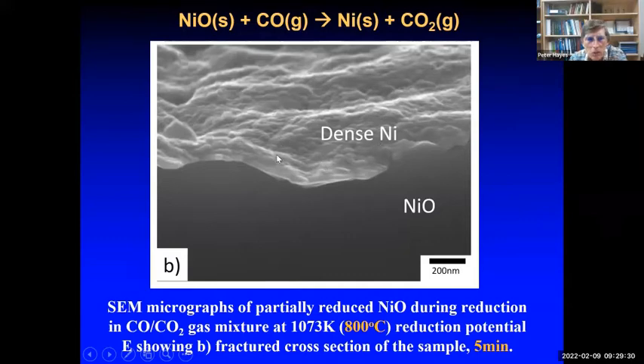So in this case, we actually stop the reaction because the gas can no longer access the nickel oxide underneath. So there's an impervious layer between the gas phase and the dense nickel oxide. Clearly, this is going to have an effect on the rates of reaction because we can't supply the CO directly to the nickel oxide surface. Any reactant has to go through this dense layer.